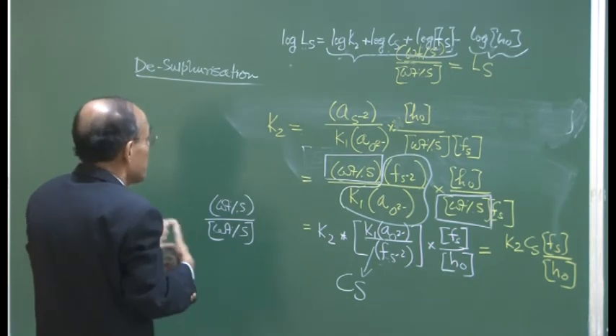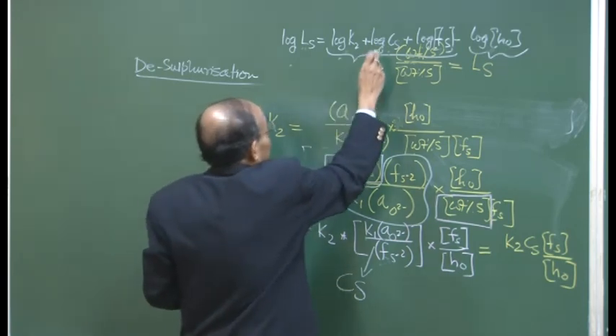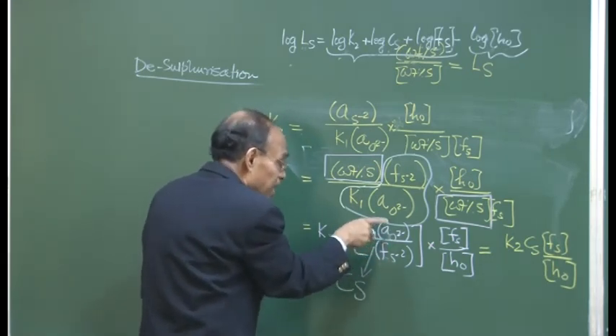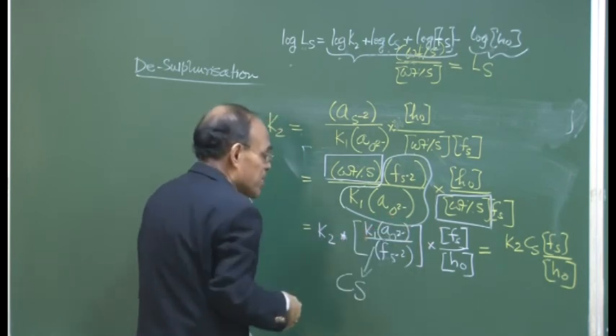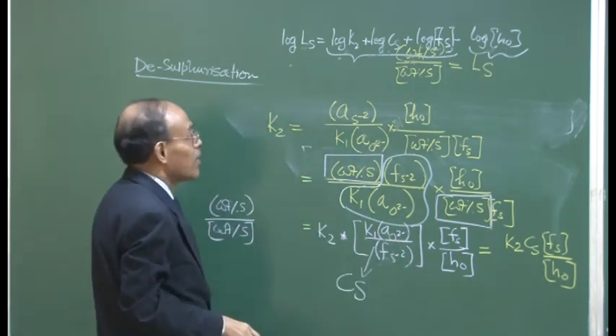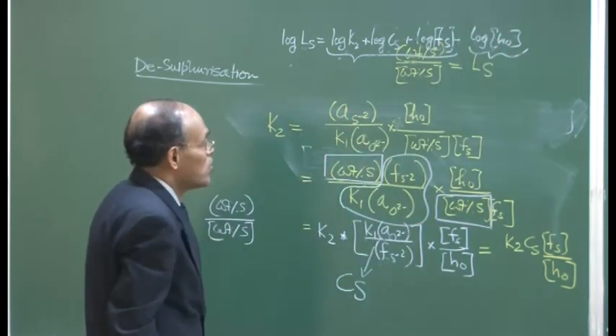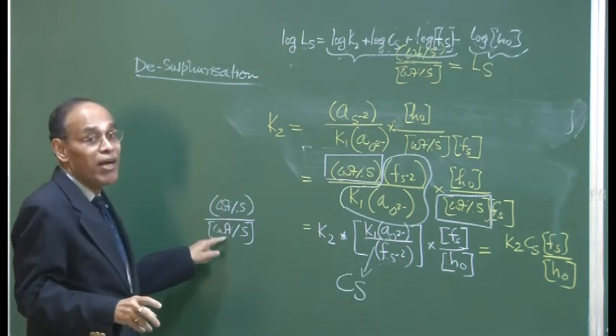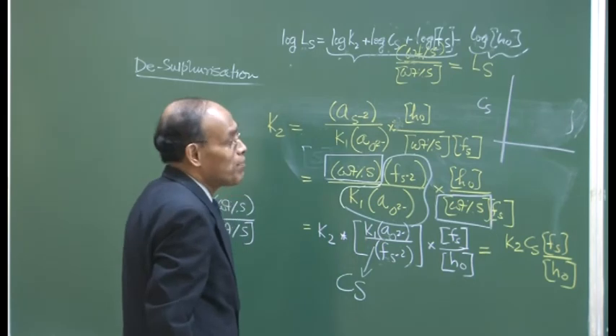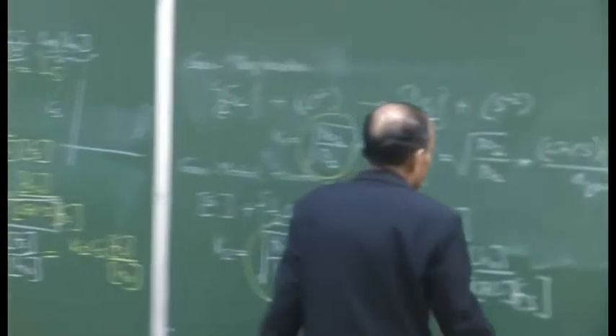So that creates a scenario for obtaining a higher partition coefficient or separation ratio for removal to the slag phase itself. And obviously, we require a large CS value, and that CS is going to be obtained if you have high lime content, and that high lime content will not only improve the anionic concentrations of calcium in the slag phase, but also simultaneously reduce the activity coefficient of sulfur in the slag phase. So therefore, a high sulfide capacity and high activity coefficient of sulfur in the melt and a smaller amount of oxygen dissolved in the melt are all conducive to obtaining a high partition ratio in the system itself. And as I said, the CS has a unit of weight percentage, as you can see here, that if you write down, the activity coefficient is dimensionless. So you can check that the sulfide capacity will come out to be in weight percentage.